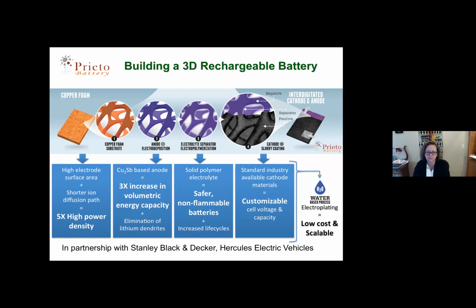Because the anode is a good metal, we can use it as the electrode to coat the whole structure with our polymer electrolyte. These are custom-made proprietary polymers that we've developed. They are good electrolytes on their own, but they are mechanically flexible. So they expand and contract as the anode lithiates and delithiates. And in theory, this leads to a much safer battery because we don't have any free electrolyte. The high rate data I will show you today, though, to be very clear, is not a dry polymer. We do gel it with a little bit of a liquid electrolyte. Again, there's no free liquid, but there is liquid gelled in the polymer, and that's what enables very low temperature performance and also the high rates.